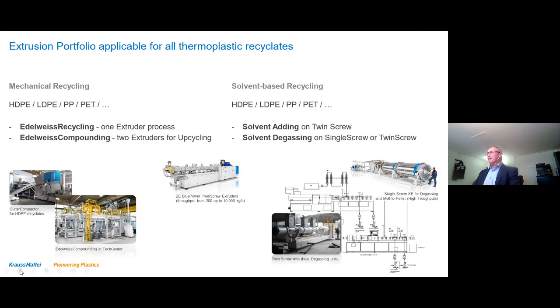At the right hand side, you see the solvent-based recycling, for different polymers. We have solvent adding processes, like for PET with the glycolysis process, and we have solvent degassing processes, which more or less fit a little bit to what Jaap just told, that we have to degas the residuals coming out of that process on extruders. Next slide, please.